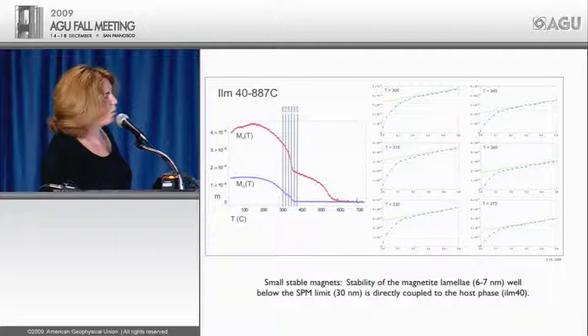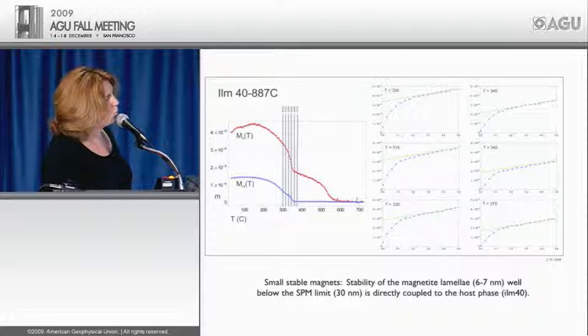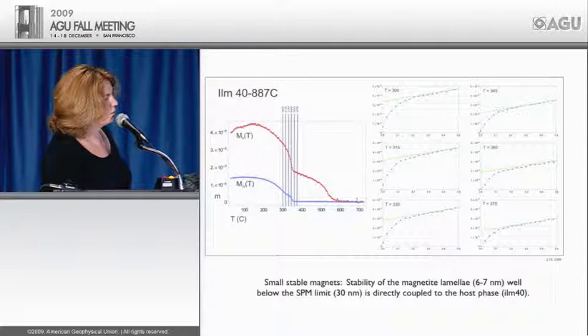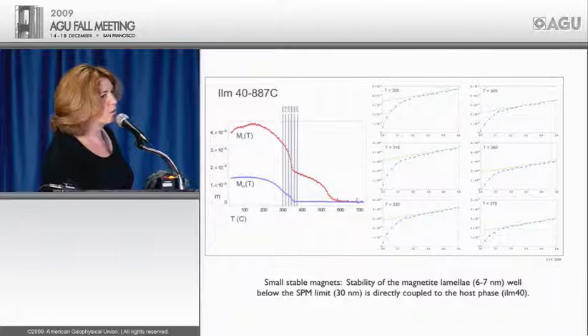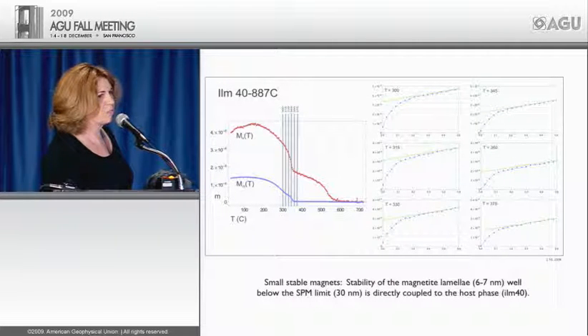But if we look at the MRS, the remanence there, we lose both the ilmenite 40 and the magnetite. And the reason it has a magnetization, those small grains, is they're coupled to the ilmenite. And as soon as that ilmenite loses its magnetization, those very fine lamellae can no longer carry your remanence. But they will still have an in-field magnetization to them.